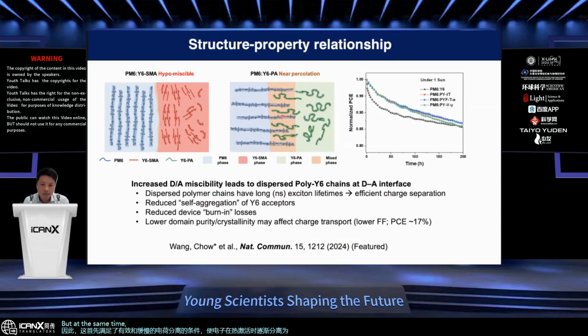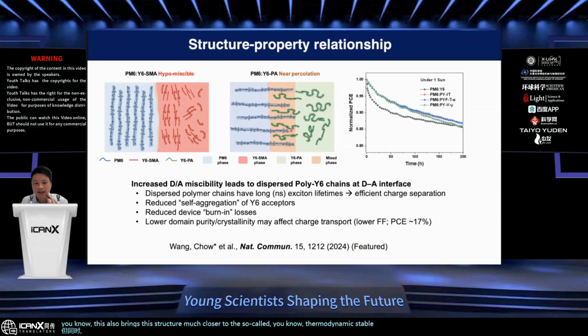But at the same time, this also brings this structure much closer to the so-called thermodynamic stable phase. And in fact, this is the reason why the device stability is also improved when we polymerize the Y6 acceptors. And we see this in experimental data. But a note is that the reduced domain purity and the crystallinity may also help us explain why the charge transport performance may also be slightly reduced in these materials.